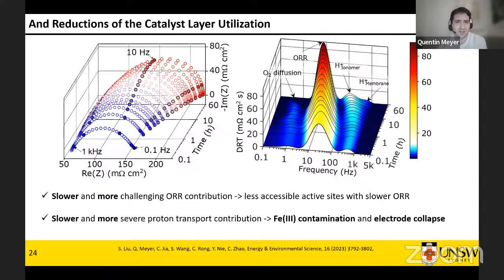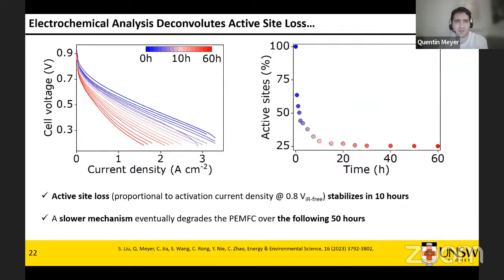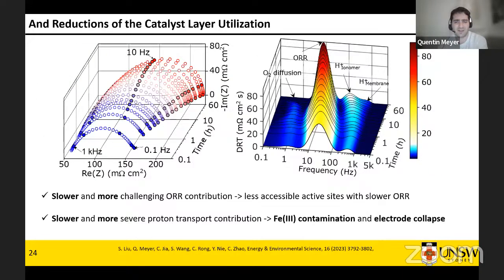And now let's look at this from our fuel cell perspective. So these two techniques, polarization curve and cyclic voltammetry, the problem they have is that they're captured very quickly and they don't quite give you the state of the cell as it's operating. Cyclic voltammetry in particular, when you run CV, you assume that you don't actually draw much current, so all the active sites that are present are reachable and there is no proton transport limitation, so you just capture what's there. Now, looking at impedance spectroscopy, we get a quite different picture.